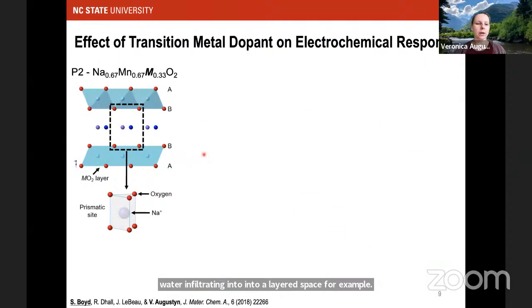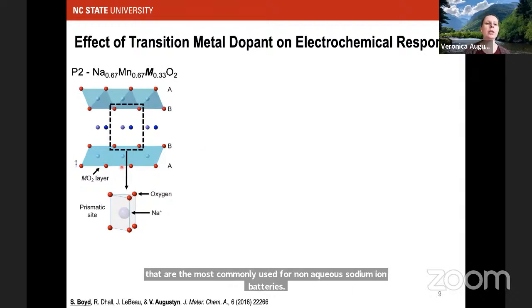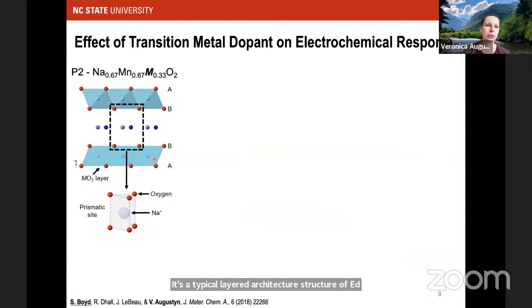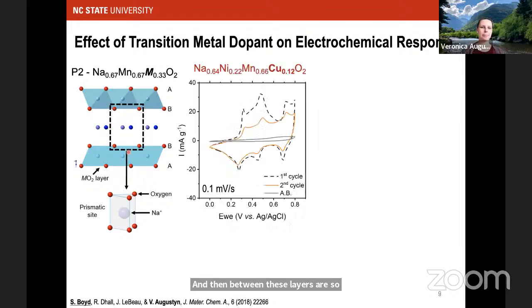So where we started the project is we said, okay, let's take a look at these P2 layered sodium metal oxides that are the most commonly used for non-aqueous sodium-ion batteries. It's a typical layered structure. You have edge-sharing MO6 octahedra. This is manganese rich, and you can change the other transition metals, usually first row transition metals, for cost and sustainability purposes. And in between these layers are sodium cations in a prismatic site.